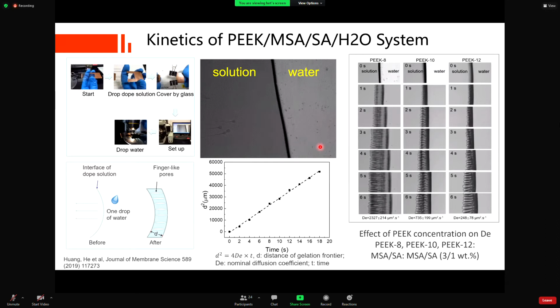The second methodology we need to use is to analyze the kinetics of the polymer system in immersion precipitation. Let me show how this works. Here you see when we put water next to a polymer solution, they will start to demix. We analyze the distance of this demixing line against time. You measure the slope of the distance against time. The slope is called the nominal diffusion coefficient. It's a characteristic of how fast the demixing is for the polymer membrane system.